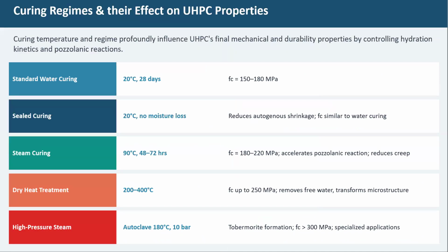And there are different curing regimes that can be followed in UHPC. The standard water curing is generally something that can be followed. But when we use steam curing, that's where we attain better strength. So in the current research I'm working on, we are also focusing on steam curing, where we are seeing the strength can drastically increase by up to 30 to 40 megapascals. But again, that may not be feasible in real-time scenarios, particularly with steam curing.